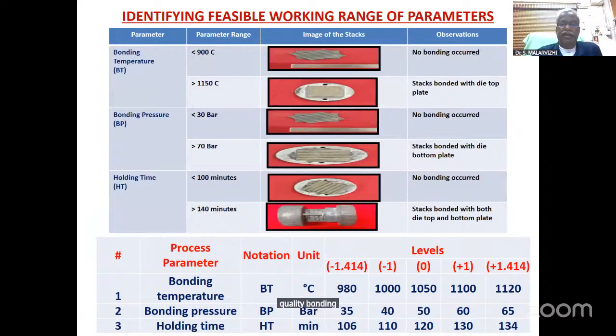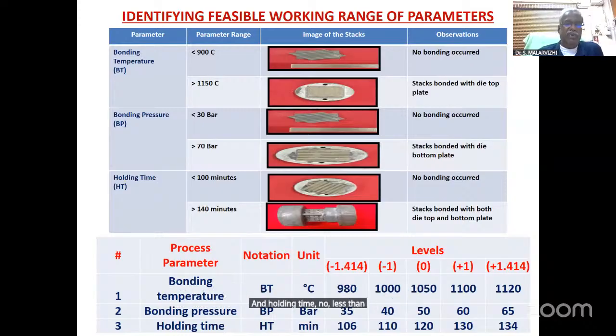Similarly, the pressure: less than 30 bar, no bonding has occurred. Above 70 bar, the stacks again bonded with the die plate. So deformation takes place, and they bonded with the die plates. And holding time, less than 100 minutes, no bonding. If you use more than 140 minutes, again, the bonding is taking place here. So within this range of temperature, pressure, and holding time, we need to optimize.